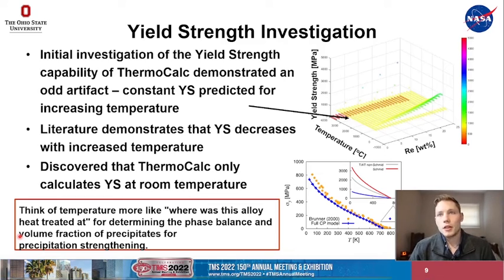Looking at the yield strength, we were expecting to be able to enter a composition and a temperature and get out the yield strength at that temperature. The thermodynamic software that we were using provided the results shown in the figure on the top right, where we have temperature on one axis, the rhenium content on the other axis, so this is a tungsten rhenium binary system, and then the yield strength on the vertical axis. As you can see from the figure, there is a lot of range of temperature where the same yield strength is predicted. This goes counter to what we expected and what you see in literature, where in the literature graph you can see that with increasing temperature, the yield strength decreases. This makes sense for most materials.